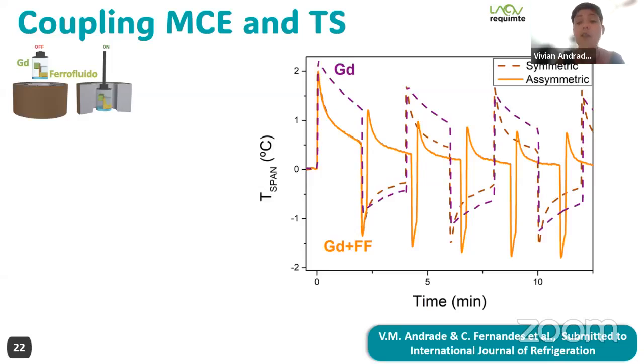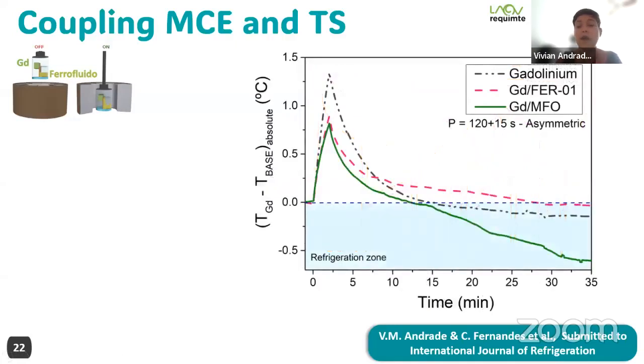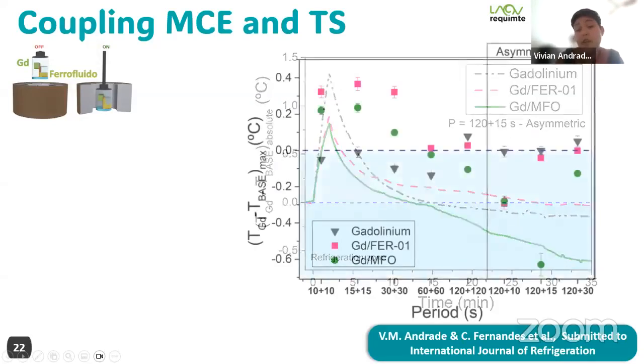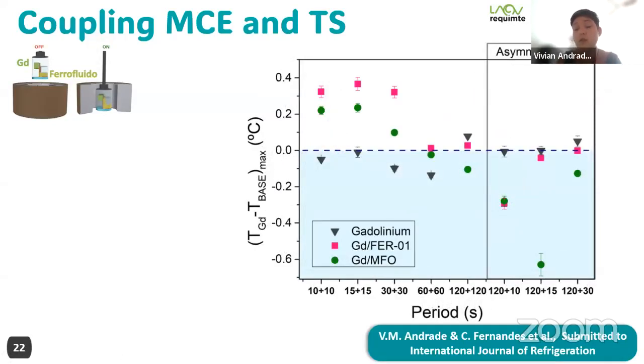And what we observed is that the temperature span reduces faster, and we could reach 0.6 Celsius degrees of variation when we put the system 2 minutes inside the magnetic field and 15 seconds outside the magnetic field. So asymmetric cycles promote the temperature span in this type of system.